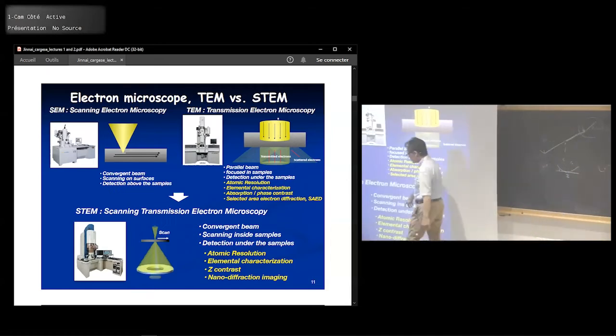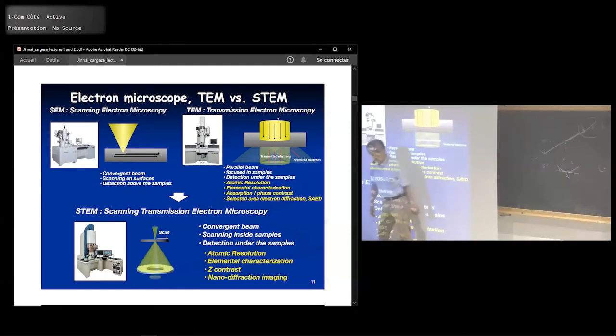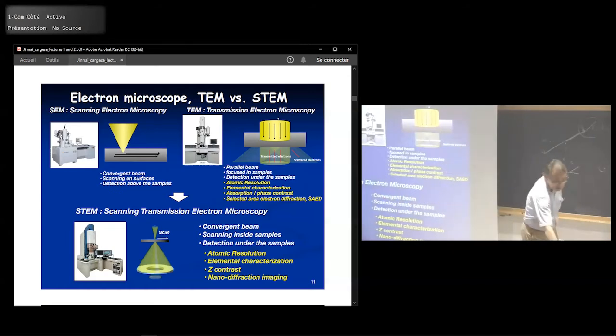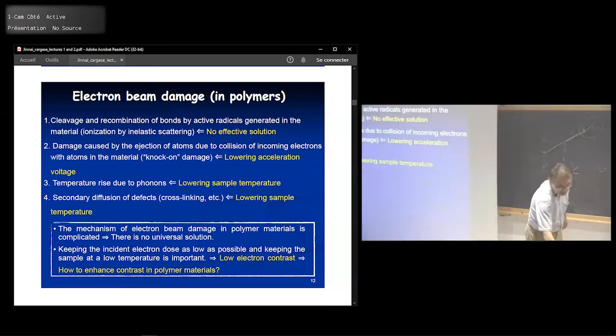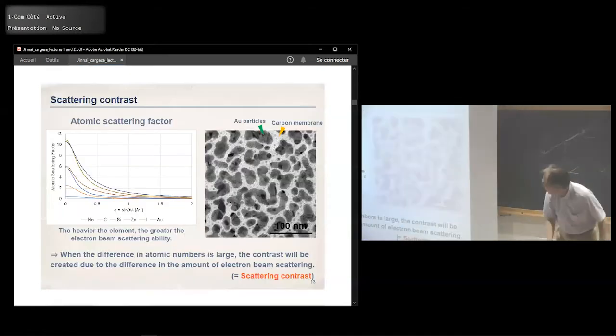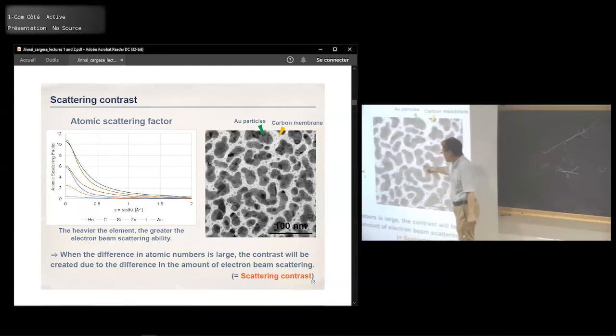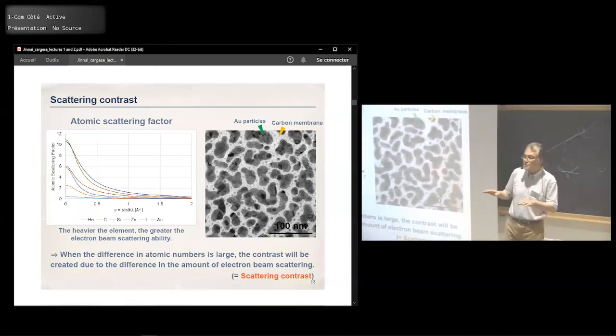Whereas for the STEM, the image should be inverted because the gold scatters very strongly towards the high angle, and the carbon also scatters, but only a little bit. So if we take this STEM and place this annular detector at the high angle, then the gold appears brighter, and the contrast will be inverted compared to TEM. So this part will be brighter, this part will be darker. So depending on which mode of the electron microscope, the image is going to be different. That's one thing you need to understand.